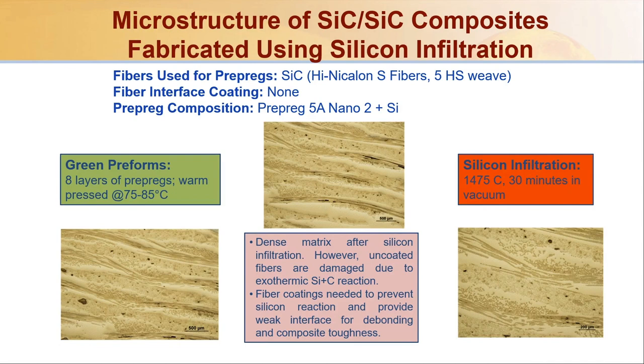So the next step was to take these laser cut prepregs and try to make green preforms. We basically used 8 layers of prepregs, which were warm pressed at 75 to 85 degrees C, and then they were pyrolyzed and then silicon infiltrated at 1475 degrees C for 30 minutes. The point I would like to make here is we had a fairly dense matrix, so there is no porosity and you have a very good carbon and silicon carbide. Of course, these fibers were not coated, so due to the silicon infiltration, you have a reaction with the fibers as well. But this prepreg composition was fairly good and useful to basically make a dense composite.